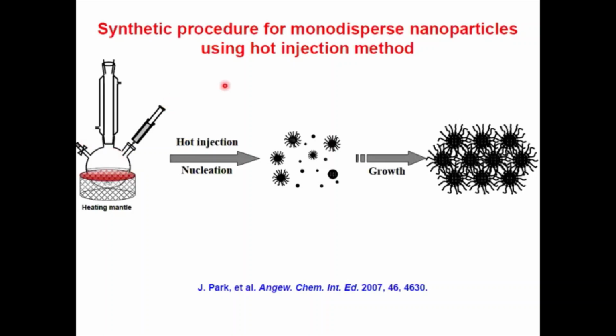Usually on one arm there will be a supply of nitrogen in and nitrogen out, and then we condense everything using the condenser unit and supply the precursor through one neck of the 3-neck flask. The surfactant or coordinating solvent is kept inside the 3-neck flask and heated. So this is a hot solution, and then the cold one is injected to make a hot injection. The nucleation we control with the burst nucleation, and the slow growth we control within the surfactant volume. This gives you control of size and shape as well as selectivity. But selectivity you can do by the other route also.